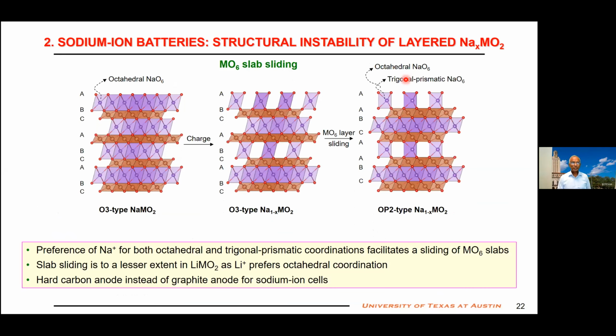To fit into my theme, I talked about sodium ion batteries. They are largely similar to lithium ion, but there is an additional challenge. Lithium generally prefers mostly the octahedral site. Sodium prefers both the octahedral site as well as the trigonal prismatic site. So they have more phase transformations when you charge than a lithium ion cathode.